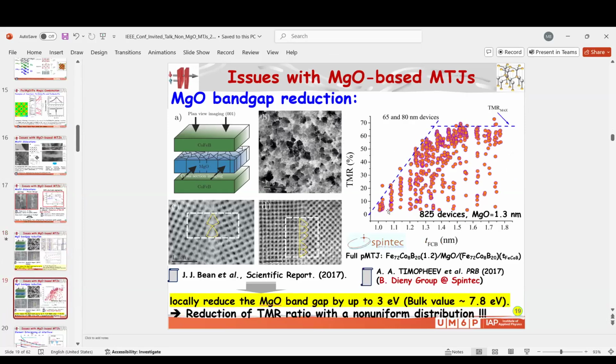In terms of thin MgO, for thinner ones, the performance becomes very bad, and the TMR is lower, and we start to have scattering and other effects. So we need to reduce this, especially for STT. I think we need a very low RA. This is handled in industry by very sophisticated technologies.